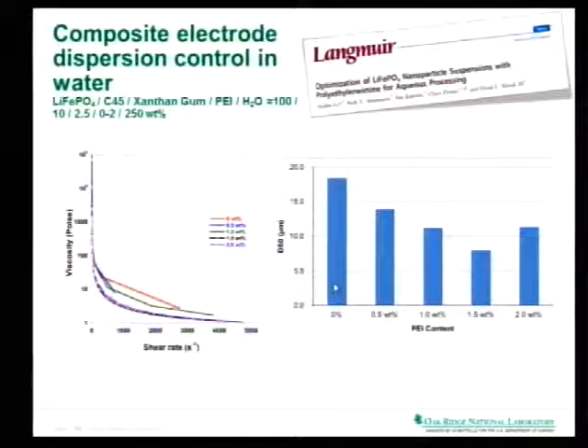So based on that characterization data, we're selecting our dispersants. In this case, we selected polyethylenimine, PEI. We put that in our system. This here is an example of lithium iron phosphate. There's also carbon black and then the binder in there. And we're looking at how we can optimize our particle size. What you see here is the particle size as a function of PEI content. And you see it goes down with a slight increase in the PEI. You want to keep that to very, very small amounts in your material. That's essentially the same technology which keeps your shampoo from having the soap all on the bottom rather than in the water, right? Things like that.